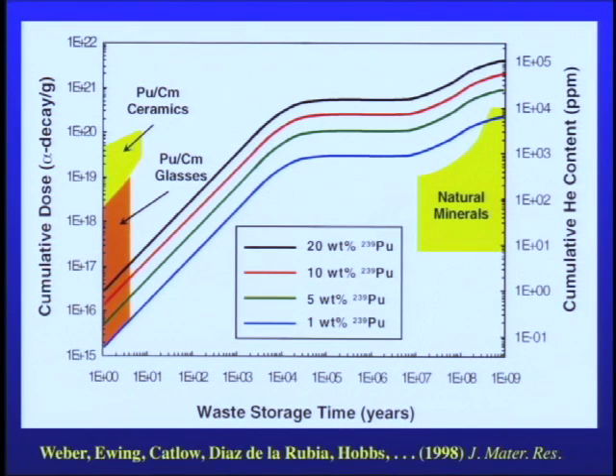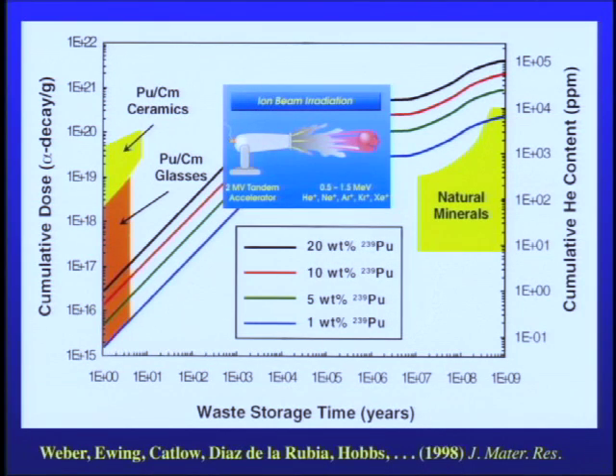Well, this can be studied by looking at natural minerals. I touched on that a little bit. It can be studied by doping things with plutonium and curium. But if we look at the dose as a function of storage time, it's in this region that you have this radiation-induced transformation. And so this is what we want to study, and this led us to using a technique not so often used in the geosciences, that is ion beam irradiation. We used heavy ions, or inert ions. We'd accelerate them at the sample and look at the damage accumulation.